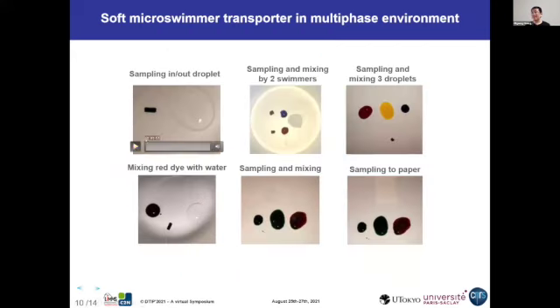So this feature of entering from a dry to a wet environment is very important, but it's not easy to realize because of the physical limitation of surface stiction and friction, especially at smaller scales. But thanks to the water absorption and the microspikes, we have minimal surface stiction, and this operation can be freely made. And then we can multiplex two of the swimmers with two different liquids, for example samples and blue or red dye. And then we can transport each of them and mix them at the target positions.